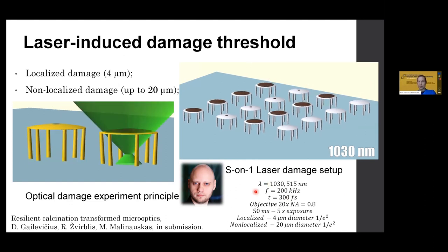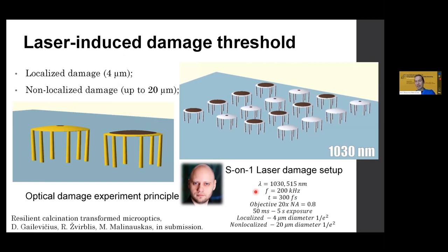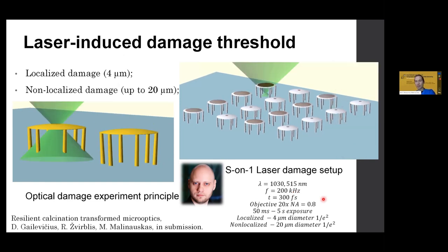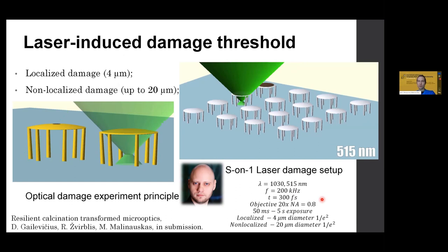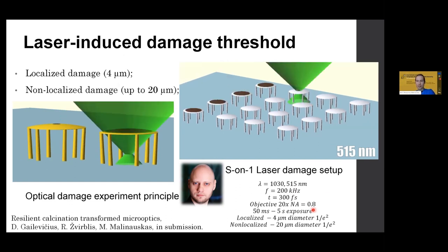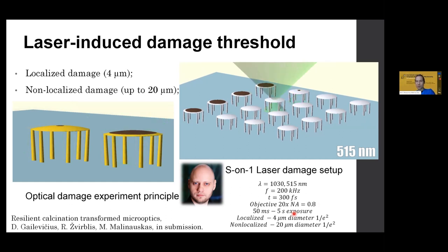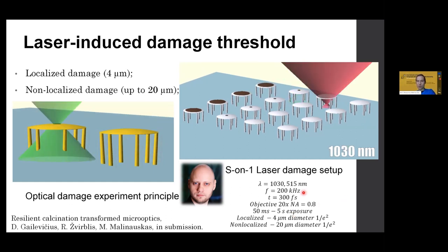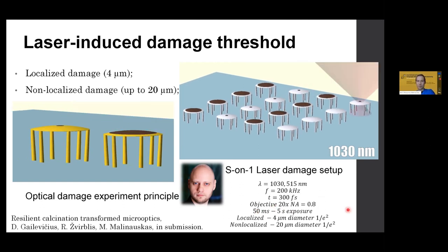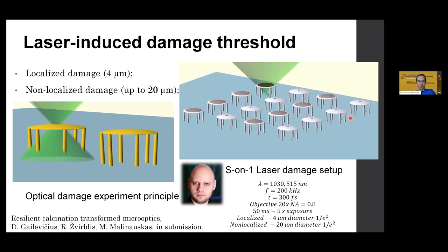Amplified laser fabrication setup. So basically, lesser pulse repetition, higher energies, so the damage threshold could be reached easily, and choosing two exposure conditions, either a short one, 50 milliseconds, or up to 5 seconds to see the accumulated fatigue on the micro lenses.